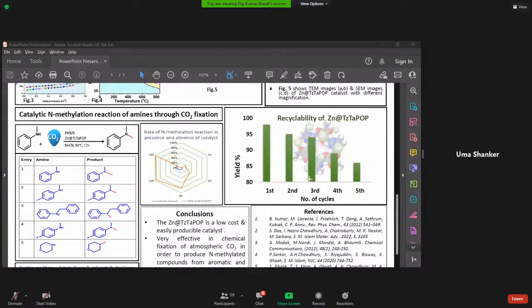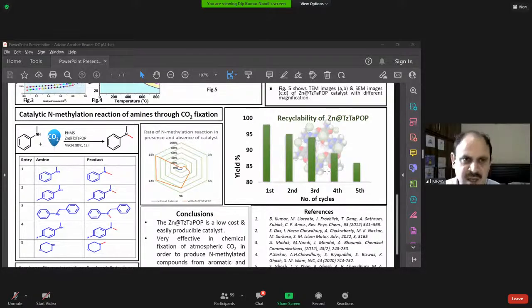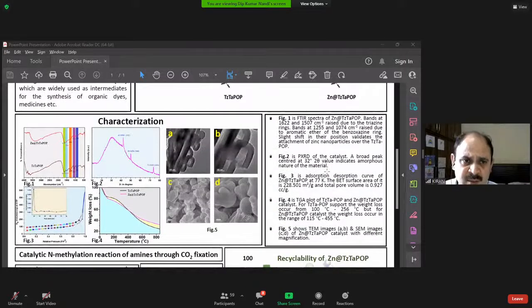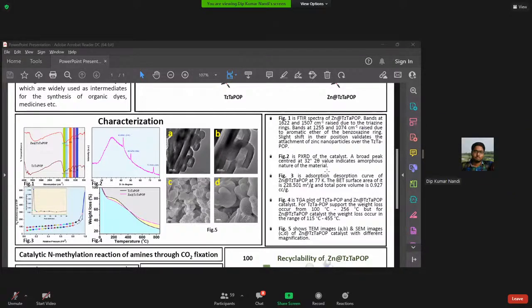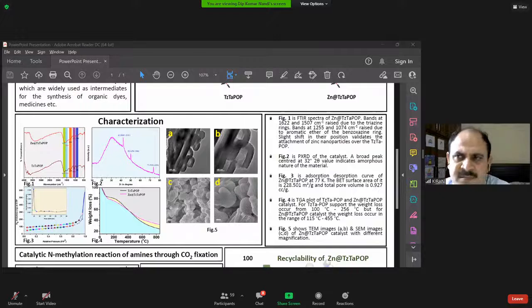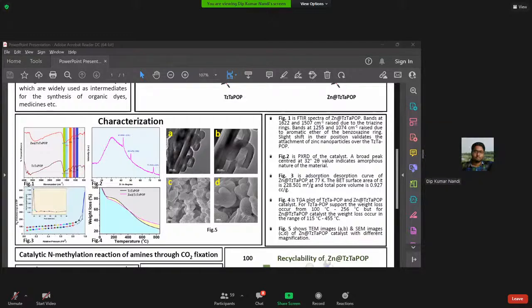Okay. Dr. Kiran, do you have any query on this? It's fine, but Deep, can you show me the XRD pattern? Go up. Yeah. So why are you having the hump around 25 degree 2 theta? Do you know what is the origin for this one? Your background is not flat. You have sharp peaks at higher angle, but around 30, you have a broad hump. Why is it so? This is because of the nature of this amorphous porous organic polymer. As you can see from literature, this is a characteristic hump we can see in such kind of porous organic polymers. So you mean it is amorphous plus crystalline? No, sir. Okay, thank you.